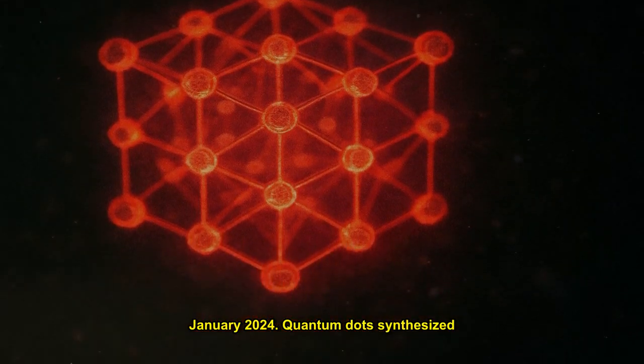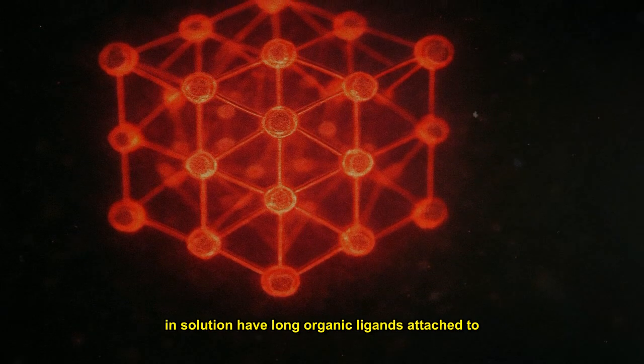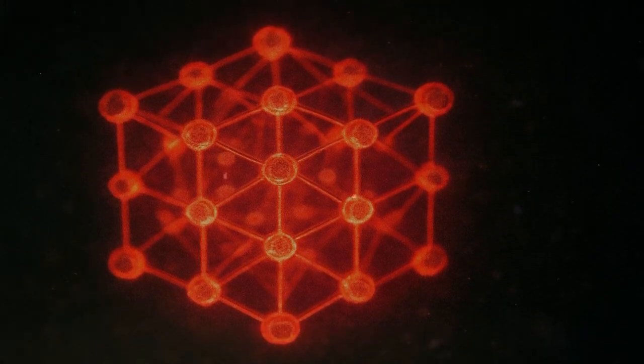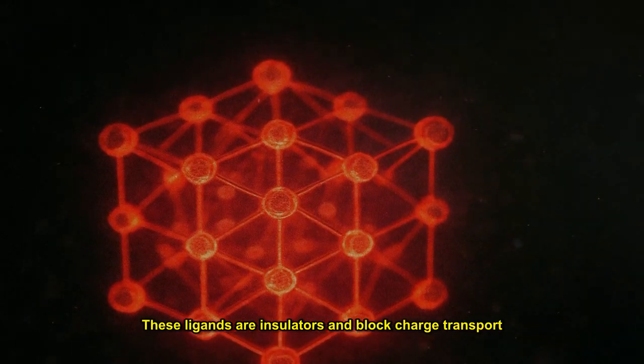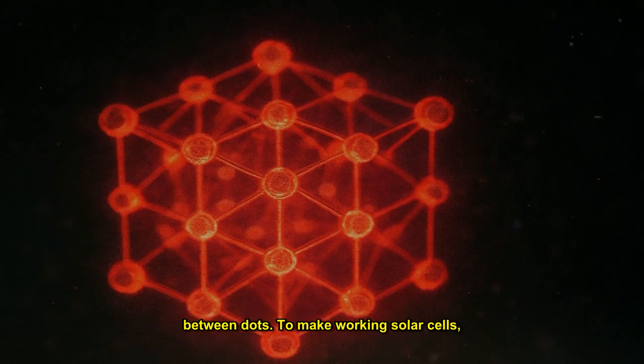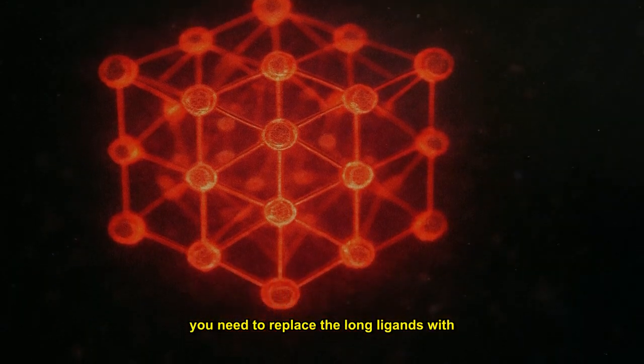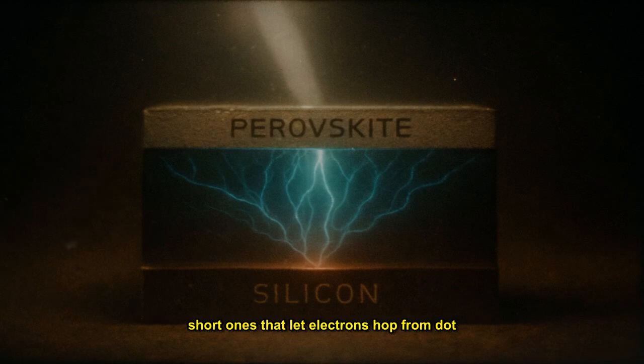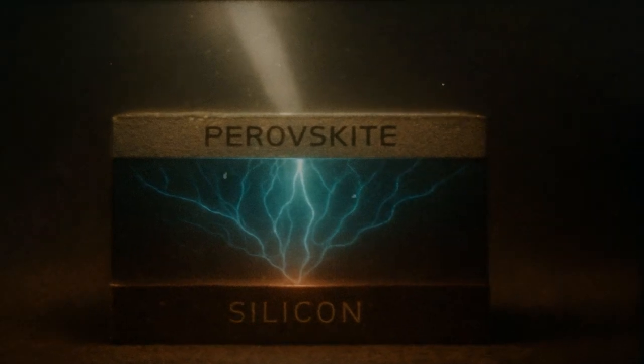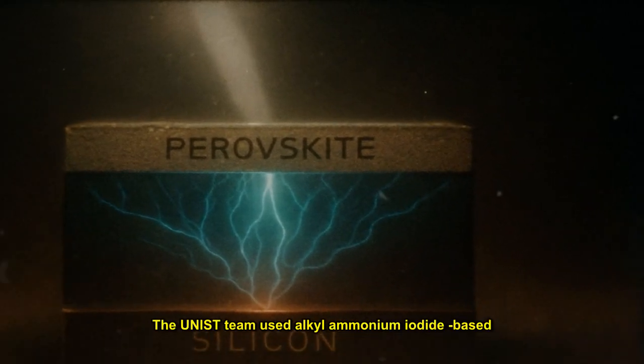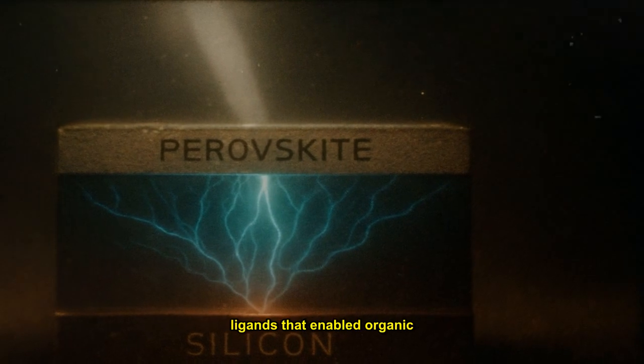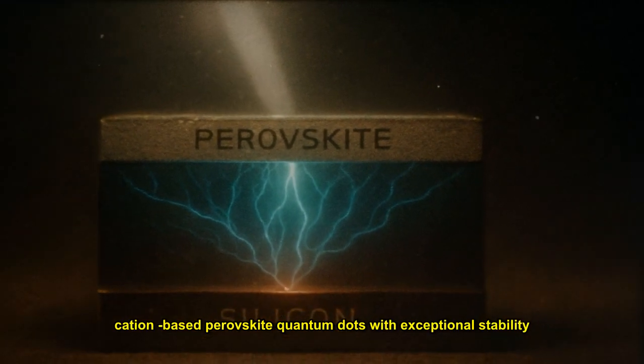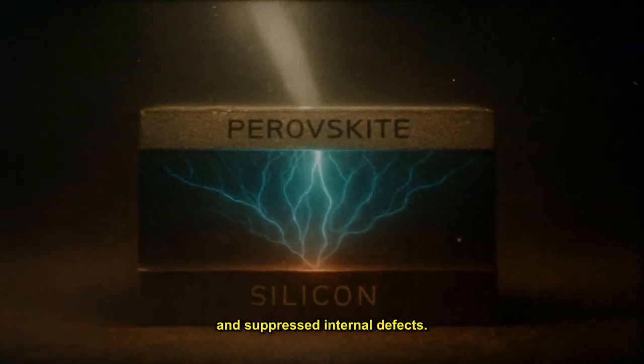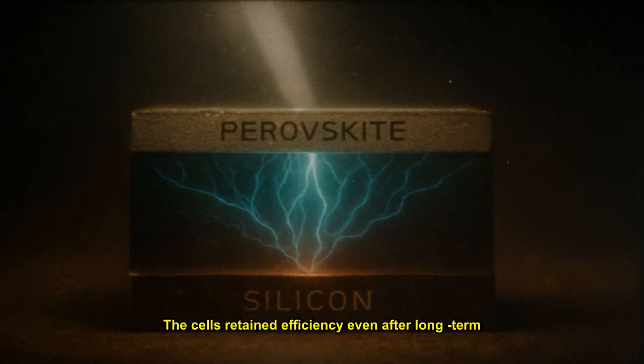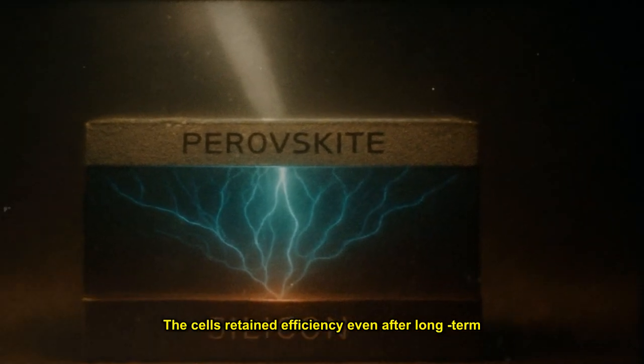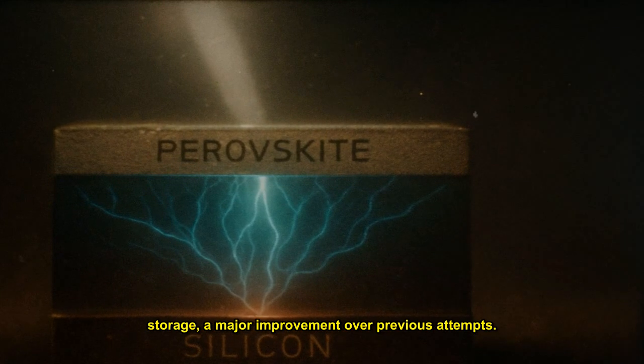Quantum dots synthesized in solution have long organic ligands attached to their surfaces to prevent aggregation. These ligands are insulators and block charge transport between dots. To make working solar cells, you need to replace the long ligands with short ones that let electrons hop from dot to dot. The UNIST team used alkyl ammonium iodide-based ligands that enabled organic cation-based perovskite quantum dots with exceptional stability and suppressed internal defects. The cells retained efficiency even after long-term storage, a major improvement over previous attempts.